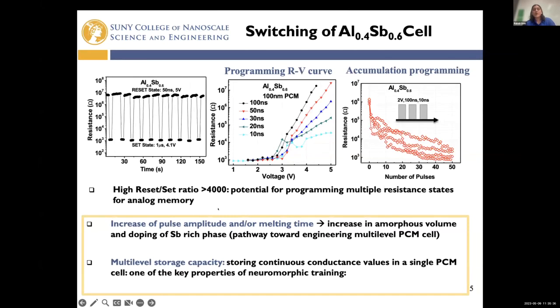One of the key properties of phase change memory is that you can store multiple resistance values within one cell, which is key for neuromorphic training, for example, matrix multiplication. There are two ways to obtain multiple resistance states. If you start from the crystalline state, by changing different pulse parameters you can obtain different resistance states. And by an accumulation property, applying the same pulse parameters multiple times, you can also change the resistance of that cell. The aluminum 40% by far shows a resistance ratio between amorphous and crystalline state greater than 4,000, which hasn't been shown for any other material so far.